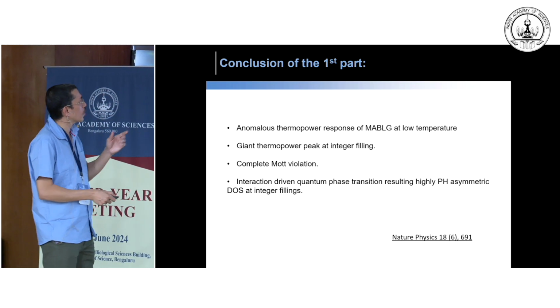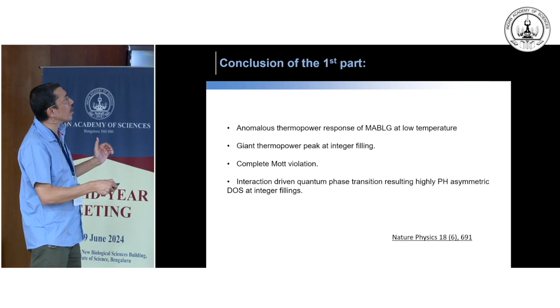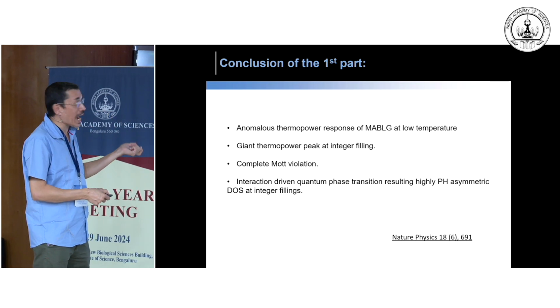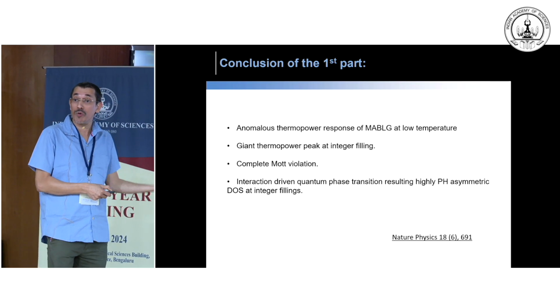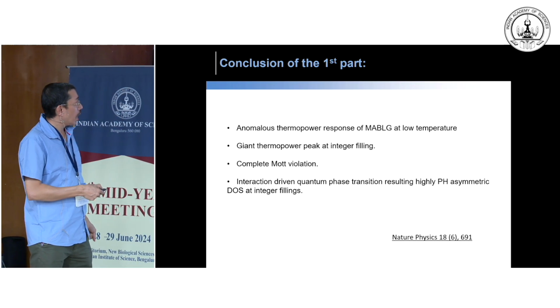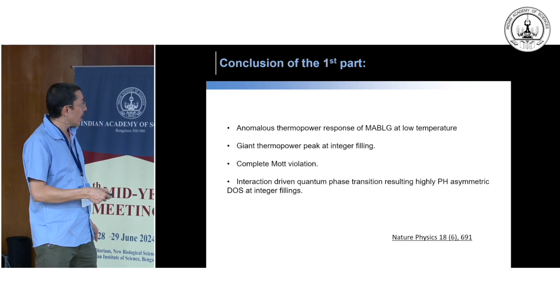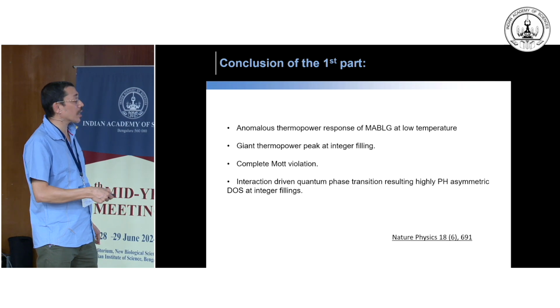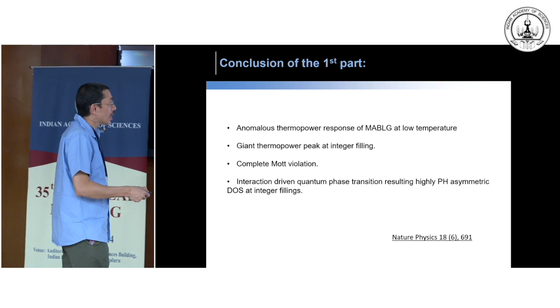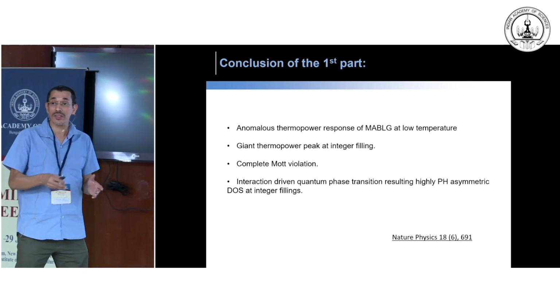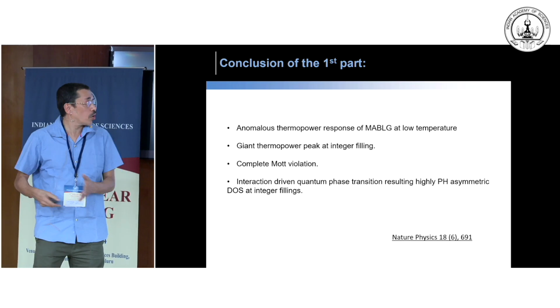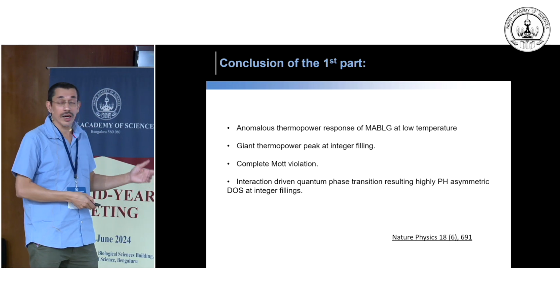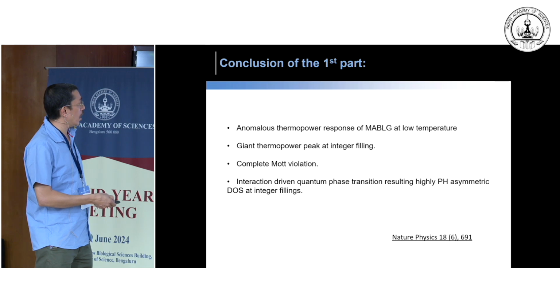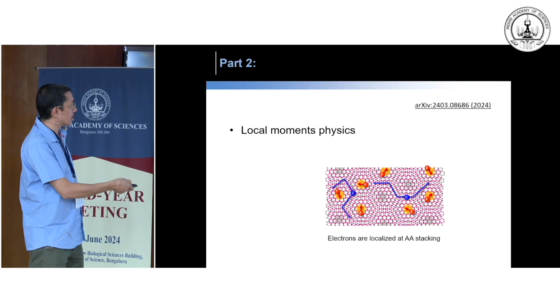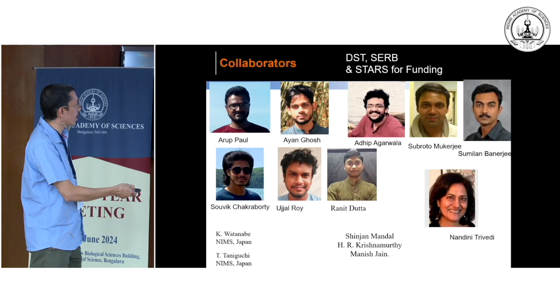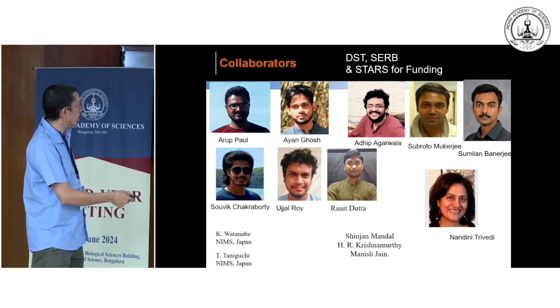So let me conclude. Unfortunately, I will not be able to talk about the second part, but what we have shown is the anomalous thermopower at very low temperature, even less than 1 Kelvin, in this kind of system, the giant thermopower at integer filling and complete Mott violation. One can understand, at least at mean field level, that interaction-driven quantum phase transitions give you the large particle-hole asymmetry, and that is the reason we see the large thermopower.